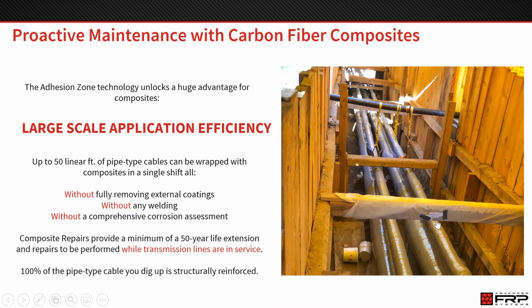They may have an asbestos containing coating on them. They may have a lead coating on them or a PCB containing coating. Any of these coatings will greatly increase the cost and the difficulty of removing the external coating. So by not having to remove it, it's a huge asset.